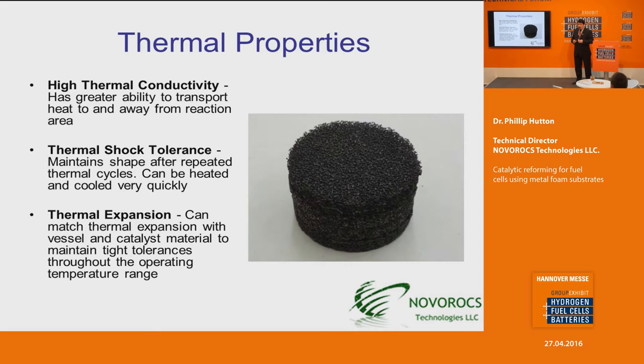Some thermal properties. If you're using a metallic foam, it has very high thermal conductivity relative to ceramic. Any reaction that occurs on catalyst is going to be either exothermic or endothermic. Exothermic meaning that it releases heat, endothermic meaning that it absorbs heat. What happens is when the reactants react, they'll either create a cool spot in the middle of the catalyst, or they'll create a hot spot in the middle of the catalyst. The higher thermal conductivity will transport heat away from the reaction zone if it's an exothermic reaction, or transfer heat to the reaction area if it's an endothermic reaction. What you want to do is maintain that temperature as uniformly as possible.